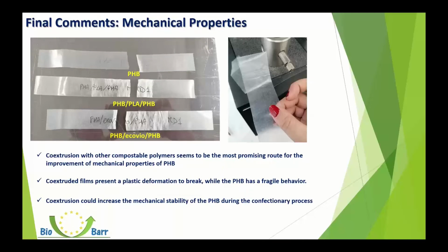And now I will make some final comments about the results obtained for the characterization of mechanical properties and barrier properties of the systems developed. The co-extrusion with another compostable polymer seems to be the most promising route for the improvement of the mechanical properties of PHB. Also, another possibility to improve the mechanical properties should be the blending of the material with other polymers, or to add some agents inside to make the material more plastic.